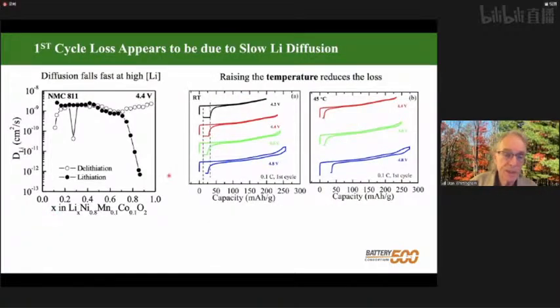So what we determined pretty quickly is that lithium diffusion is the problem. It's not clear yet whether that's in the bulk of the material or just in the surface. But the solid circles here are lithium in diffusion, and the open circles are removing the lithium. And you can see there's no problem in removing the lithium until you get to the very end. So you can do fast charging with these materials with no problem, but you have difficulty getting all the lithium in.